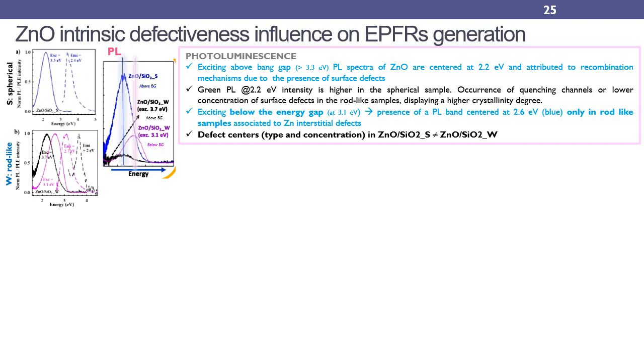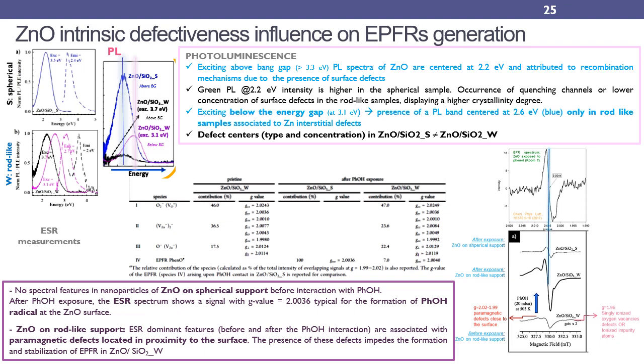The presence of paramagnetic defects has been checked through ESR measurements. Moreover, the typical process at the base of the formation of environmentally persistent free radicals has been simulated through the exposition of zinc oxide nanoparticle to phenol vapor. Briefly, the obtained results prove the presence of different paramagnetic species due to defects lying in proximity to the surface of the zinc oxide nanoparticles, whose relative contribution in the ESR spectrum is maximum for zinc oxide on rod-like silica before and also after the interaction with phenol.